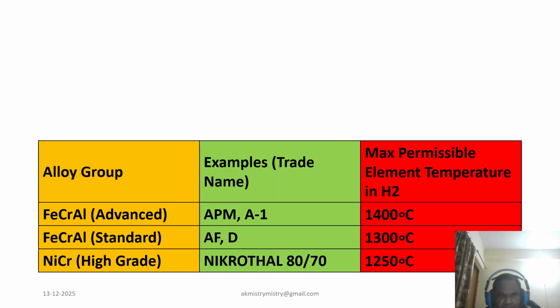Now, coming to this slide, which elaborates on how the advanced material, that is APM type A1, can withstand the highest temperature. The maximum permissible element temperature in hydrogen is 1400 degrees centigrade. Similarly, the standard grade is 1300, and nickel chromium high grade, or Nikrothal, is 1250.